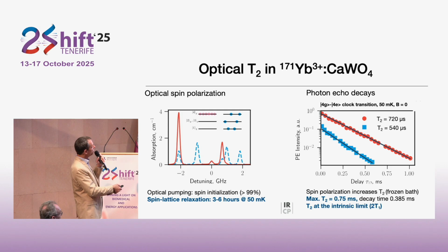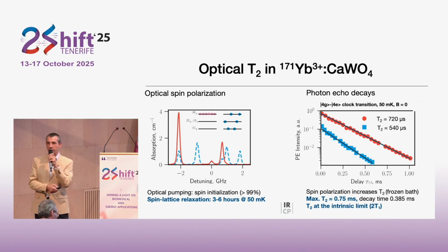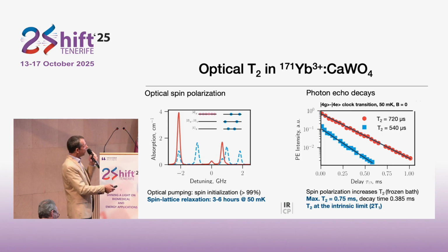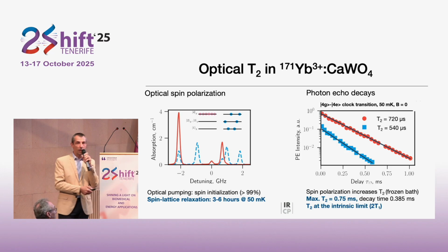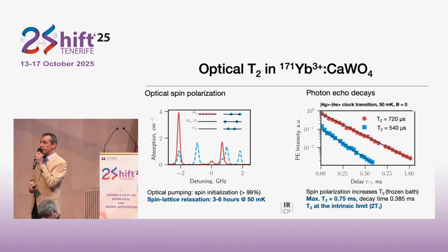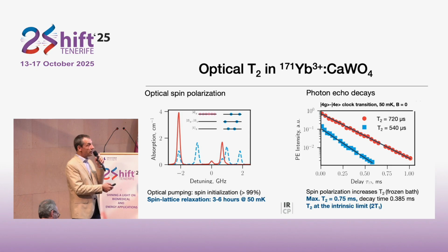So if we do not do the polarization of the spins, we observe a value of 540 microseconds. But this value is significantly increasing if we do the polarization. And now we reach, in this particular experiment, 720 microseconds. Why do we see this effect?